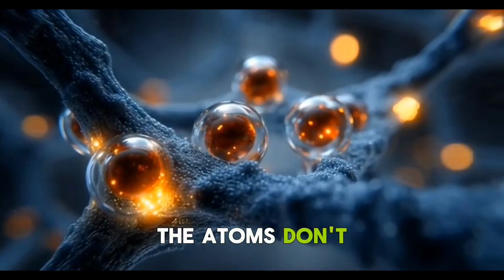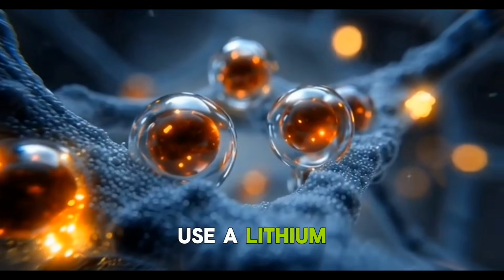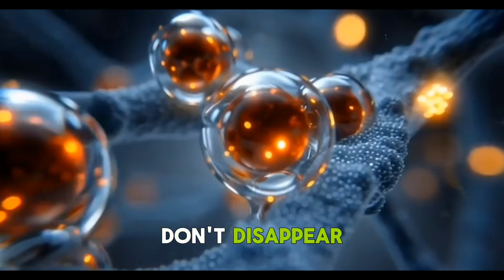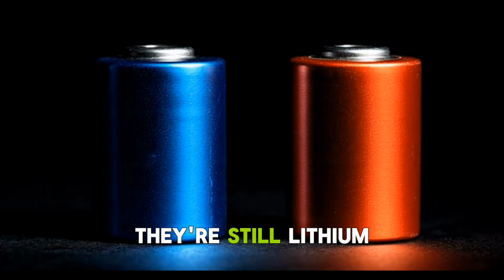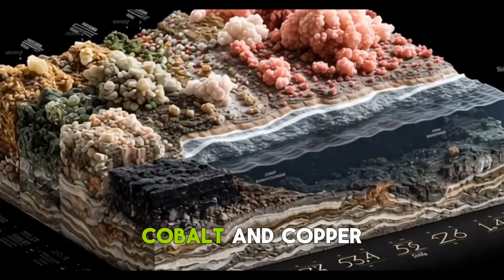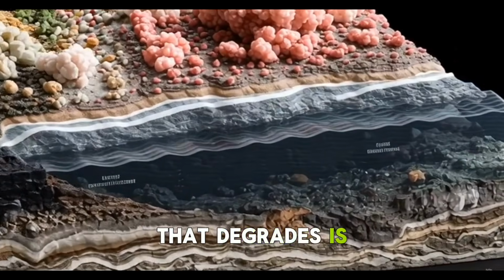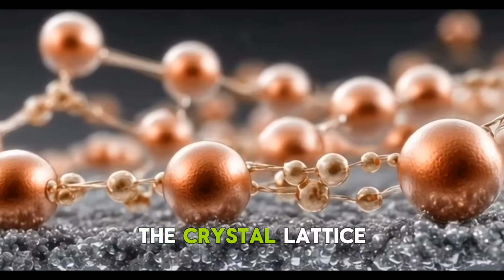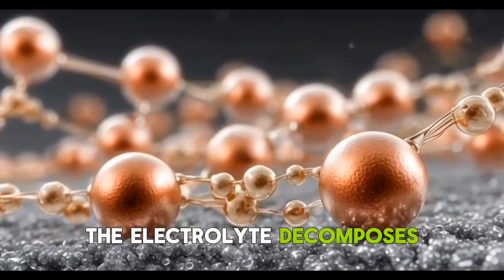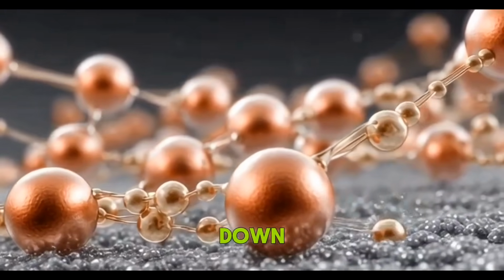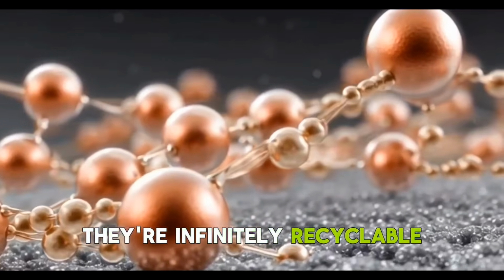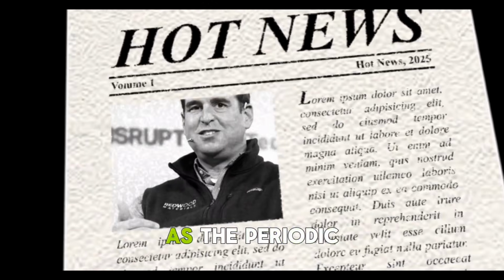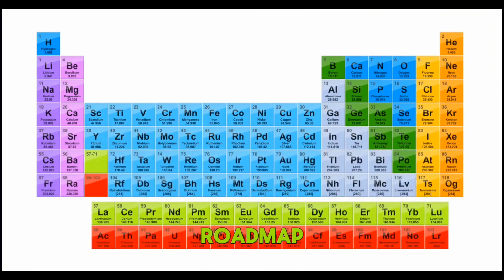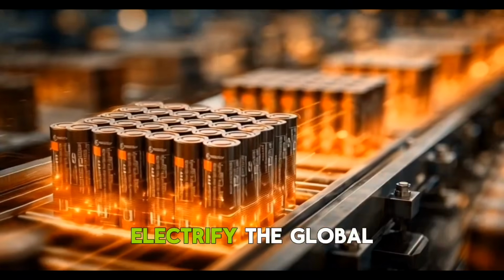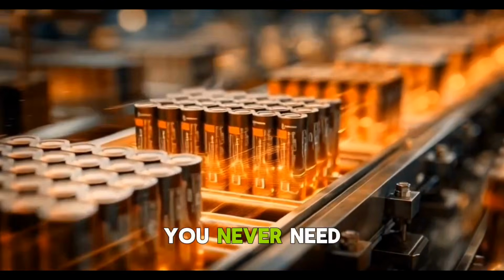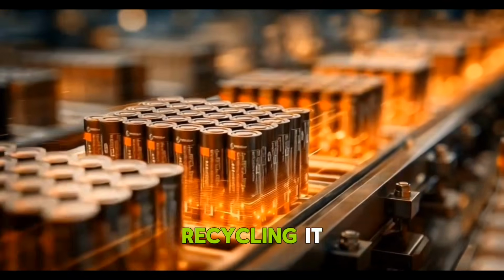But here's the key insight. The atoms don't degrade. When you use a lithium-ion battery, the lithium atoms don't disappear. They don't decay. They're still lithium. Same with nickel, cobalt, and copper. The only thing that degrades is the structure of the electrode. The crystal lattice fractures, the electrolyte decomposes, the separator breaks down. But the atoms, they're infinitely recyclable. Straubel describes this as the periodic table as a roadmap. Once you've mined enough lithium to electrify the global vehicle fleet, you never need to mine it again. You just keep recycling it.